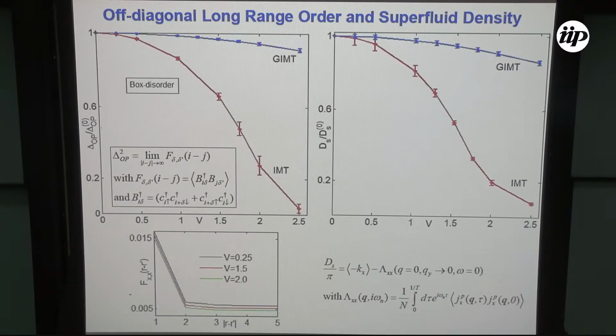So we looked at the physical observables, like off-diagonal long-range order or superfluid density. What happens as we introduce disorder in the sample? So what is off-diagonal long-range order? It's like long-range correlation. So you have a Cooper pair in a bond, you annihilate it, you create it far away. What is the probability of this process? So this is given here. If you look at the off-diagonal long-range order, we have normalized it by the homogeneous value.